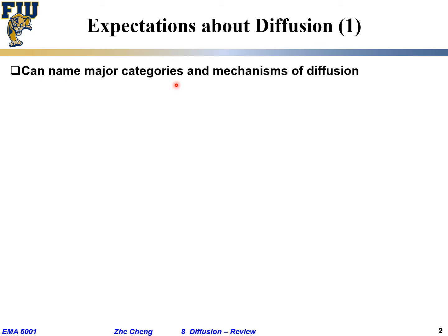There is so-called interdiffusion or self-diffusion. Interdiffusion is the situation where there is a concentration gradient. Some region has concentration that is higher or lower than some surrounding regions. But self-diffusion is for the situation where even if the material is completely homogeneous, completely uniform in its concentration, the microscopic species, the atoms, molecules are still not sitting still. They would move around through the random walk fashion of diffusion. Okay, these are different ways.